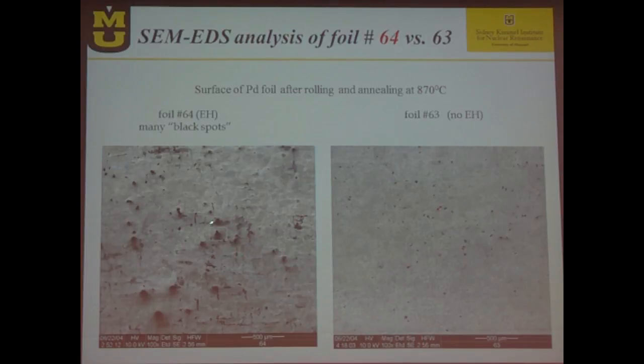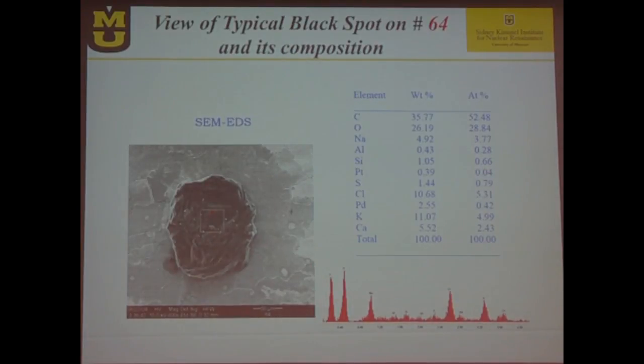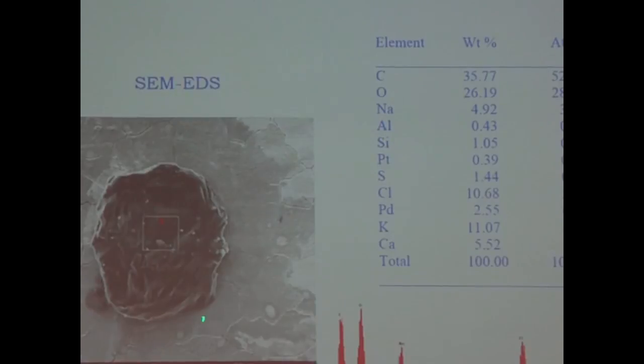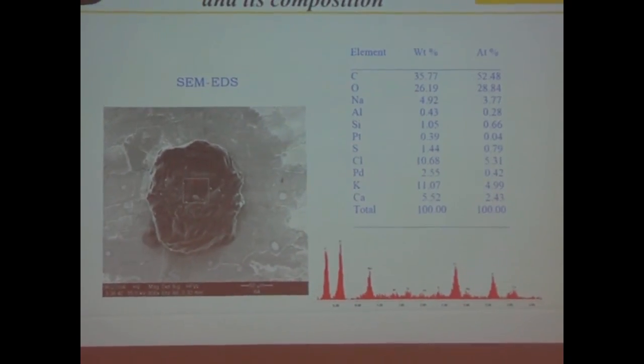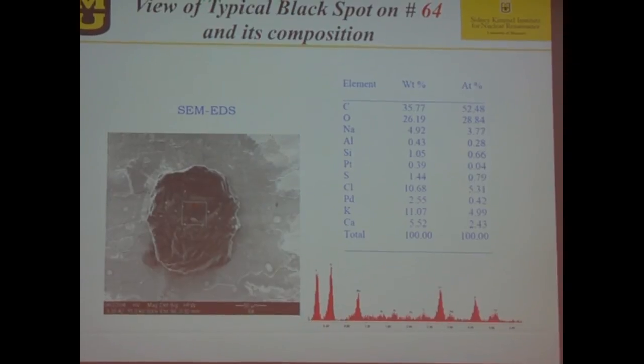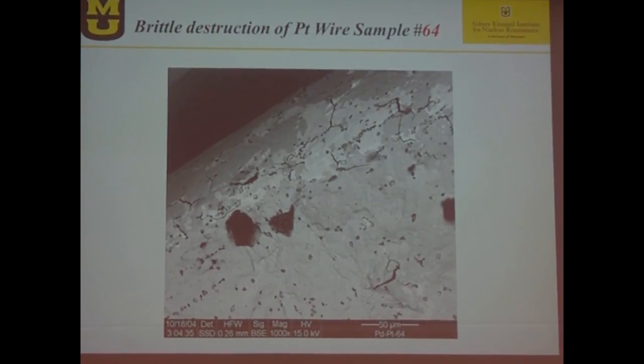Now we thought that this is due to these spots, black spots we call them, carbon spots. When you are applying the electrochemical process, actually you are creating very strong electric fields which are creating an increase of temperature locally close to these sites. So we were trying to get those spots artificially. We were not so successful. Just to give you some indication of what a black spot means, this is carbon, and we are spotting this point. You can see that most of it is carbon and some other ingredients, but that didn't bring us to good reproducibility.